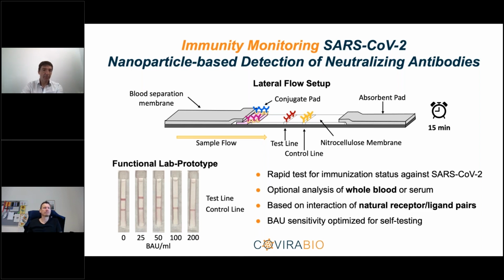And this is some examples here where we just can see the control line here. It's the prototype of this test, the control line, and on comparison here the test line, which is showing us a graduated decrease with increasing amounts of neutralizing antibodies in the samples. So the assay is compatible. It's a rapid test. It takes like 15 minutes. It's compatible with whole blood. So there's a blood separation membrane at the beginning of the strip.